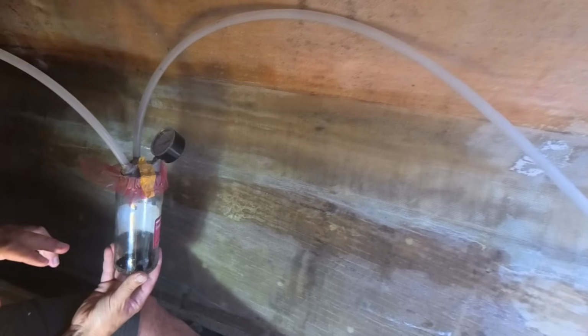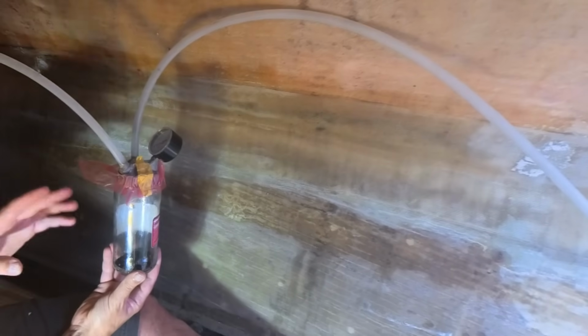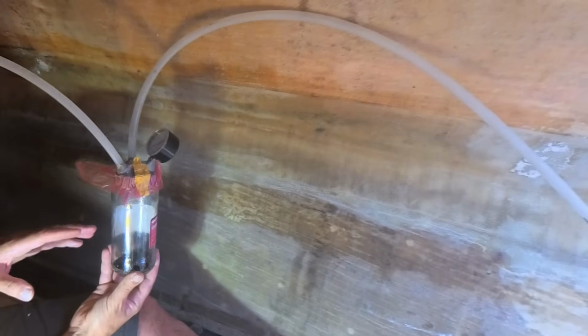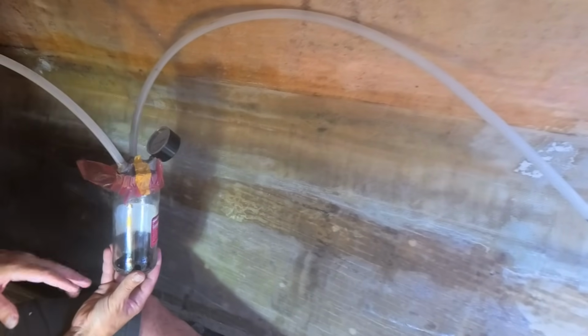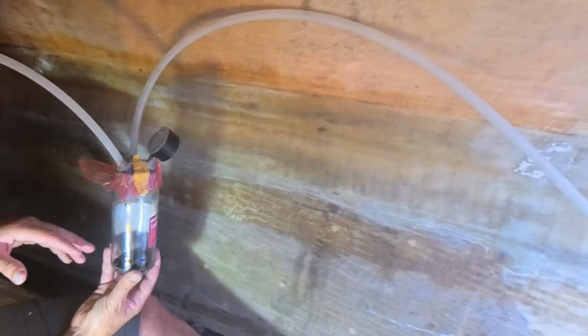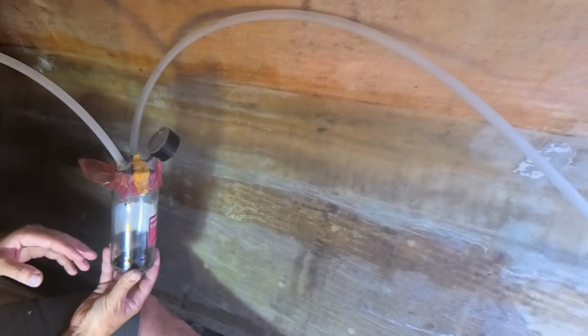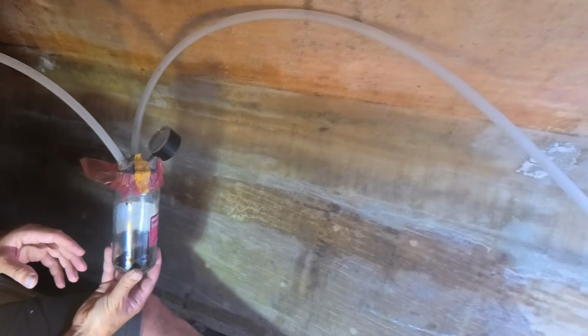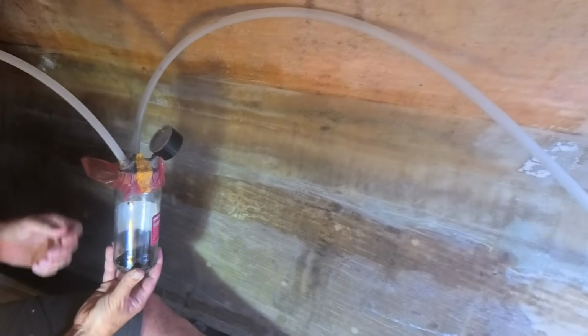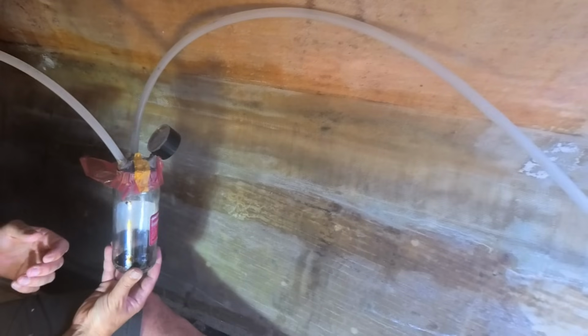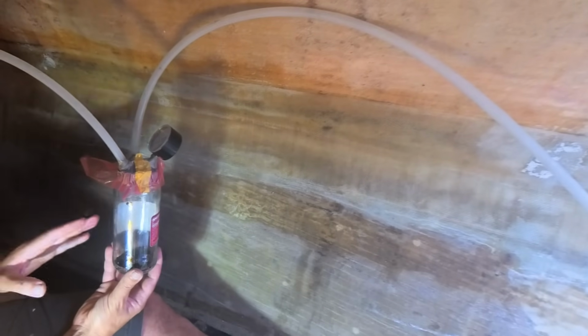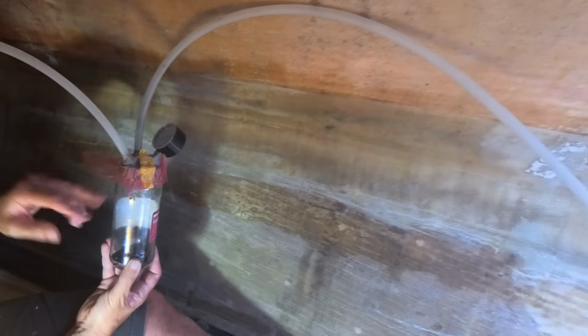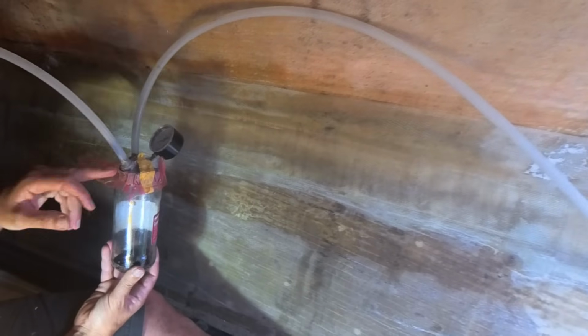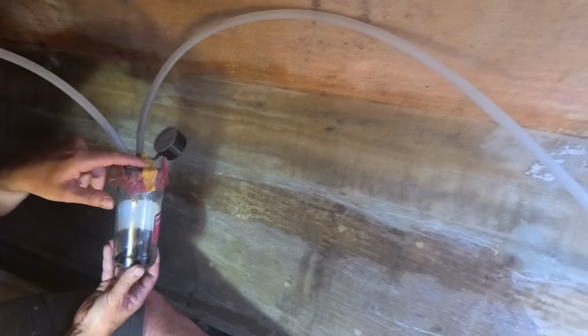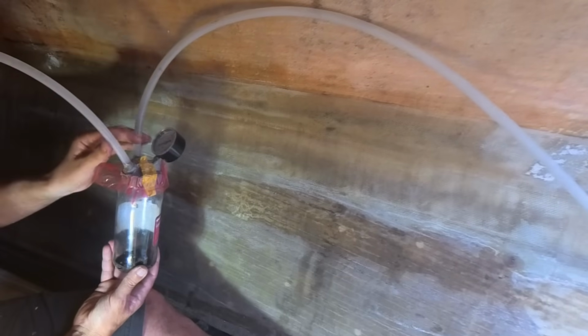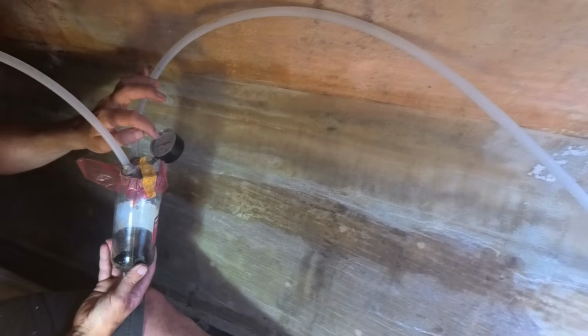What you really don't want is resin going into your vacuum pump, because it's almost instant shutdown for the vacuum pump, depending on what resin you use. When it hits the vacuum pump, it's nice and hot, which accelerates the cure of the resin, and you end up with this oil-infused, semi-cured resin that stops your vacuum pump from working. Not a cool look. So yeah, high-tech jar. In this case I went super high-tech and put a 3D printed lid on it, which accepts the diameter of the hoses and also the vacuum gauge.